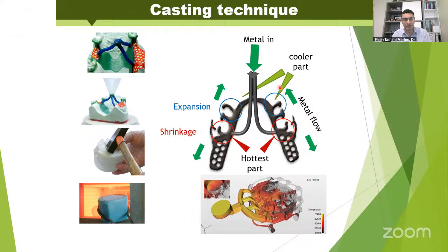The first and most basic thing is that when you're injecting hot metal, the distribution of heat in the metal is not homogeneous. You're going to have areas that are hot and areas that are cooler. That's going to create shrinkage and expansions in the framework. So by default, the simple act of casting metal causes deformations in the framework. It's impossible to have a perfect metal framework by casting.